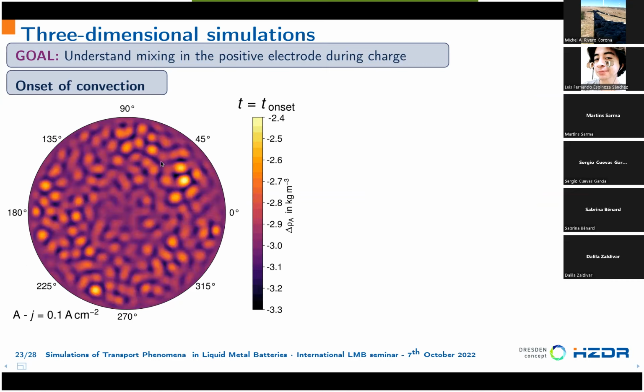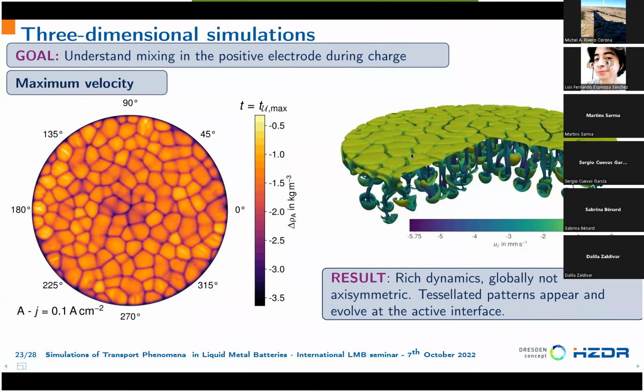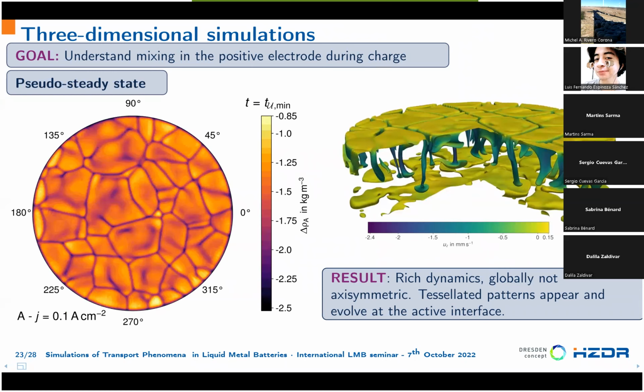At the beginning, at the onset of convection, we have this pattern forming at the interface of the electrode. This pattern is more or less like the wavy pattern that we saw in 2D, but now in 3D, with the formation of these vermicular shapes. Then convection sets in, and we have these very nice plumes and the formation of this tessellated pattern at the interface. The single plume is axisymmetric, and this is what seems to explain the good agreement with the axisymmetric case. The full flow is not at all axisymmetric, but the single component is. If we go to the pseudo steady state, these tessellated cells become larger, and the full layer is again involved in the phenomenon.